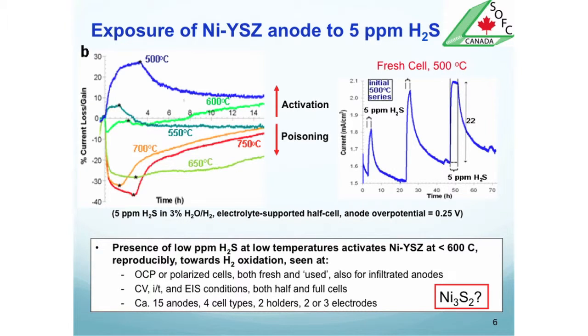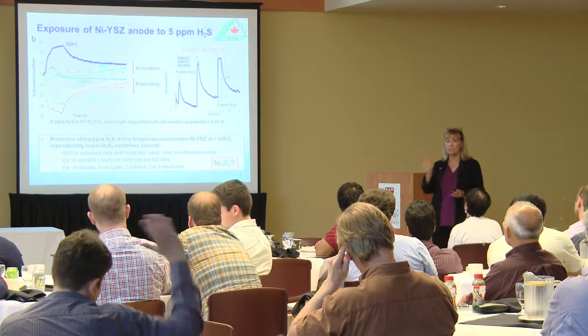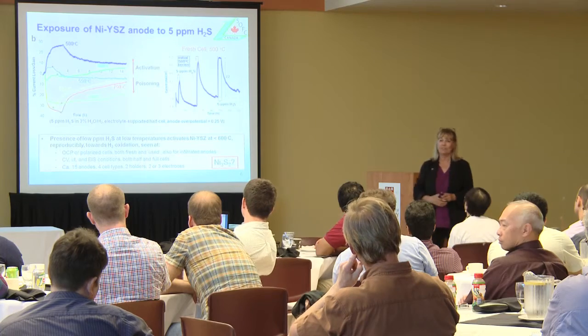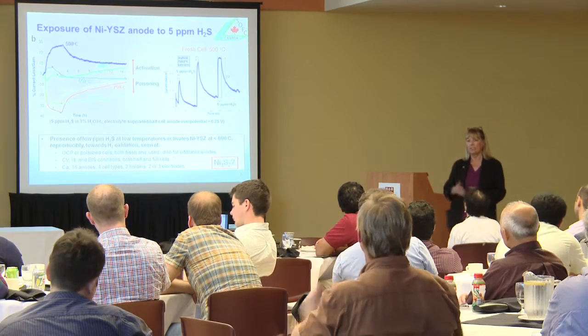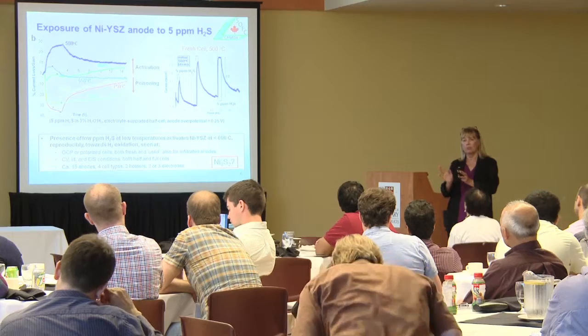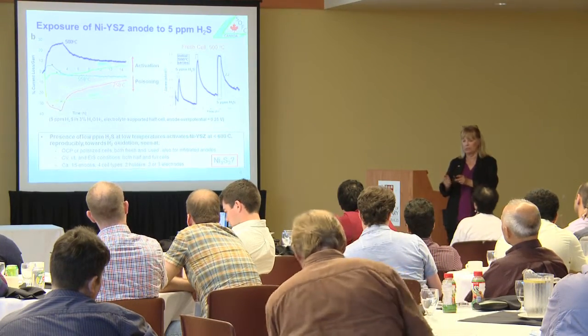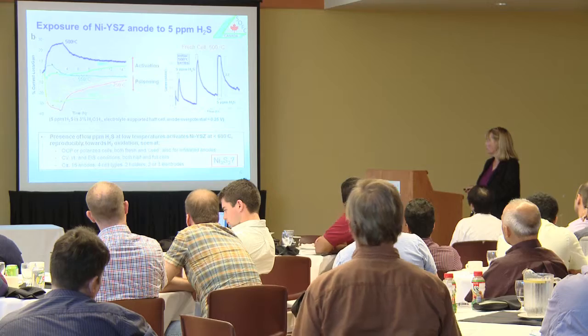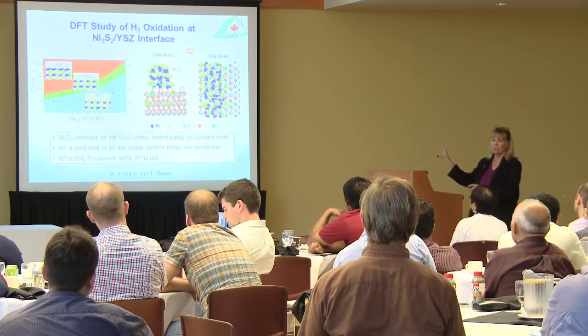At the same time, we have groups like Nigel Brandon's and Meilin Liu's, very respectable groups, who are all doing this and that with sulfur, and they do see hints of some sulfur phases in their electrodes. So there was that on the other side. So we took a two-pronged attack here. I turned to Max, wherever he's sitting, somewhere I can't even see. Thank you, Max. I might need you, we'll see. But Max and Tom on the theory side, while we pursued heavier experimentation to try to verify what we are forming. So I'm going to be quick on these next two slides.